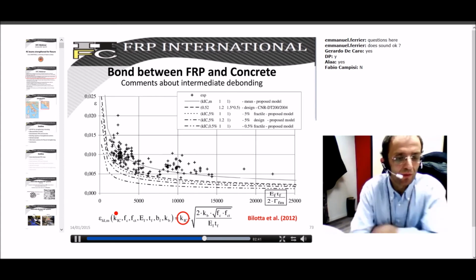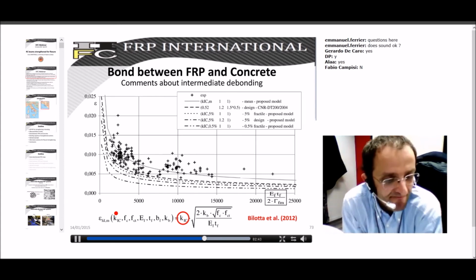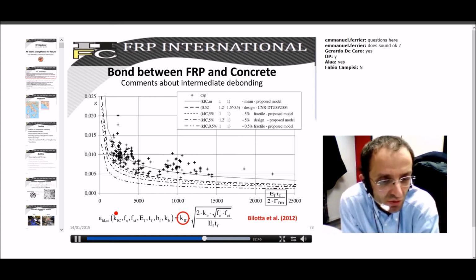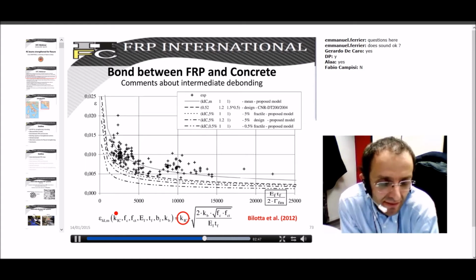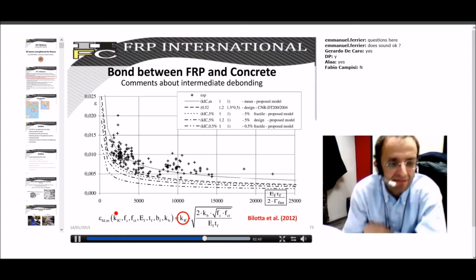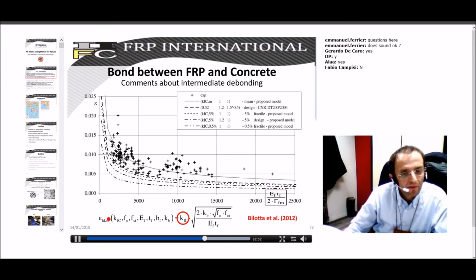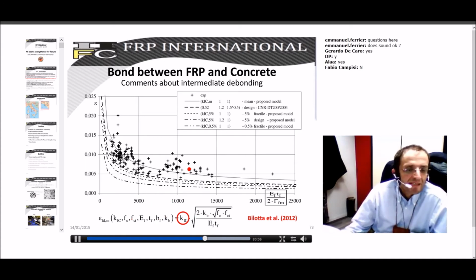Usually, what guidelines and codes do, they just provide designers with a maximum epsilon, generally lower than the ultimate epsilon of the FRP strip. So the maximum epsilon resulting in intermediate crack-induced debonding. So this is basically an empirical calibration.